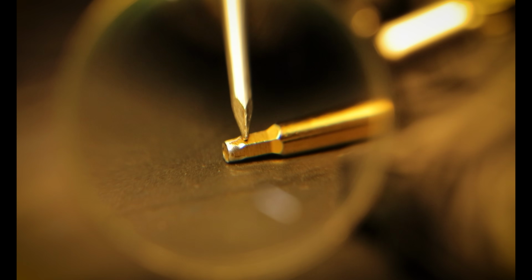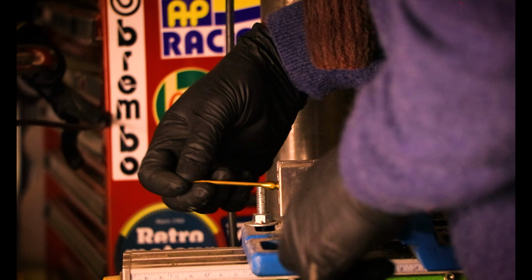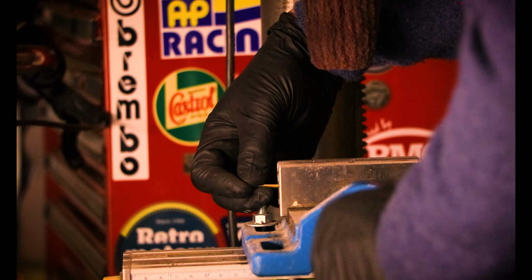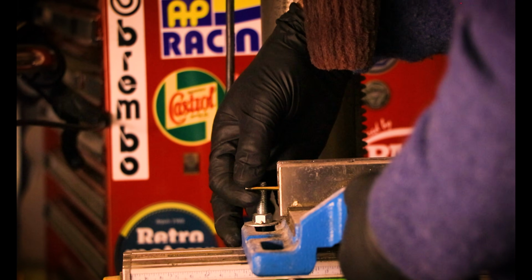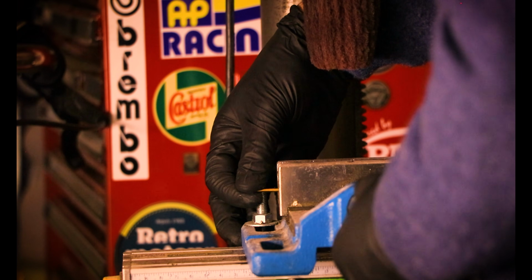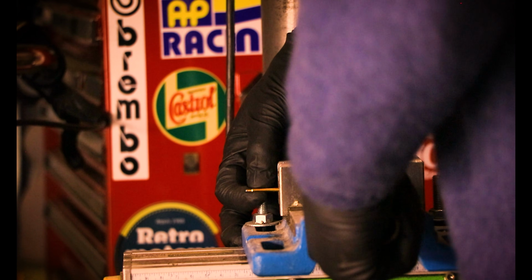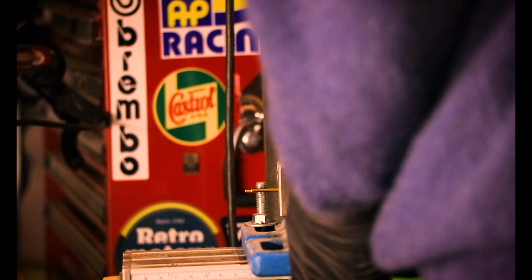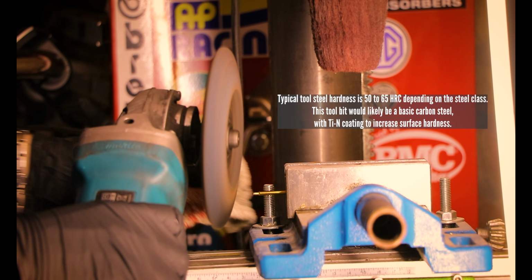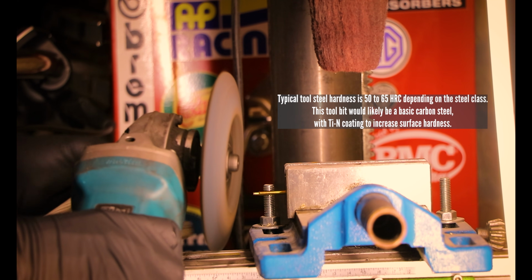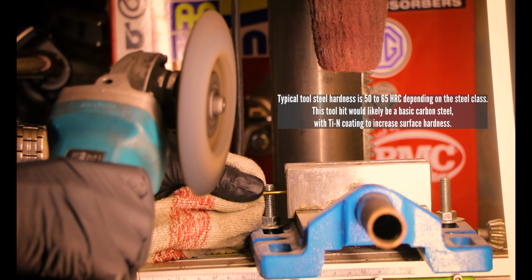However, we can't just grind it down. If you take a Dremel or bench grinder to this small amount of mass, you will generate friction heat almost instantly. You'll see the tip turn blue, grey, or even cherry red. If you do that, you've ruined the heat treat. You've annealed the steel, making it soft. It will strip again on the very first screw.